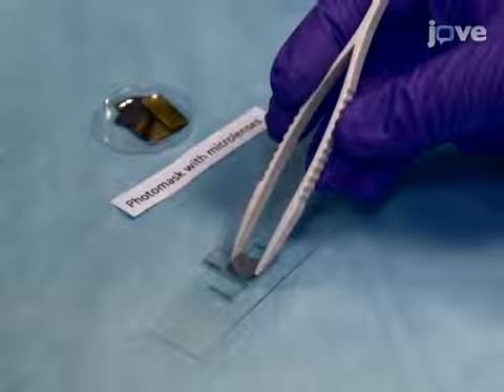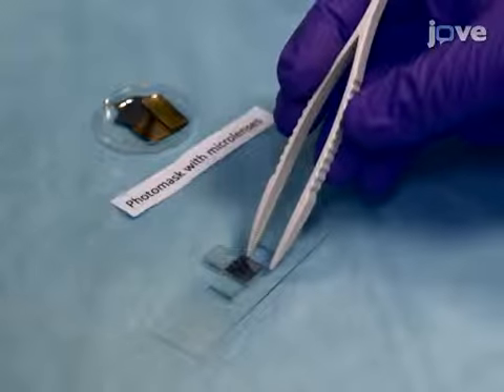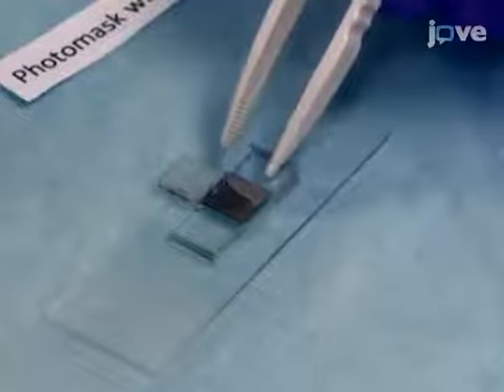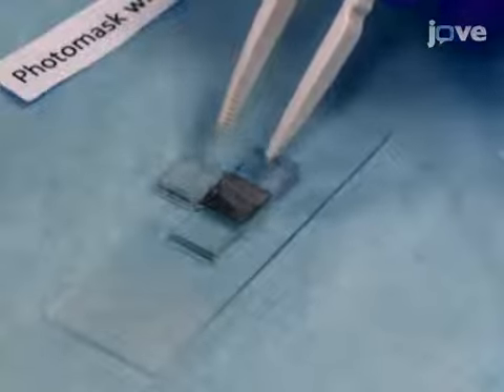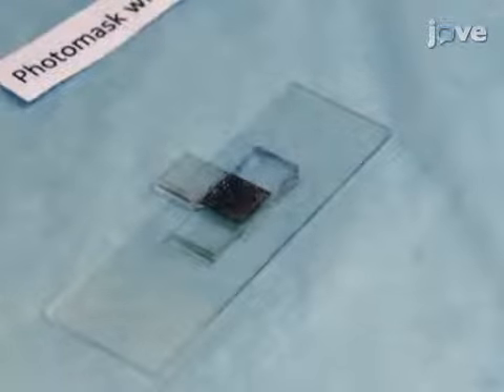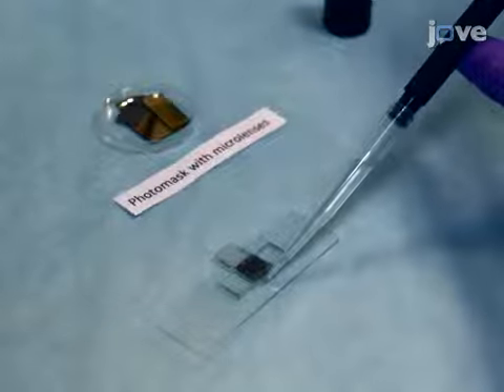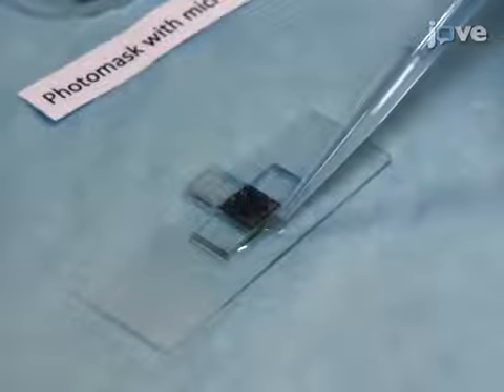Next, position the photomask so that the chromium gold-coated surface is facing the interior of the cavity. Ensure that the sides of the cavity walls are not obscuring the lenses embedded in the photomask. Fill the cavity with the pre-polymer solution until the chromium gold-coated surface comes into contact with the solution without any visible bubbles.